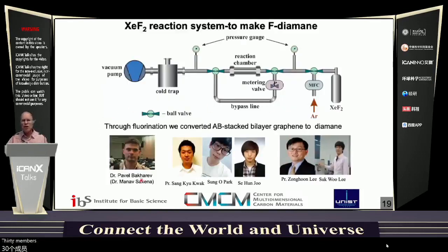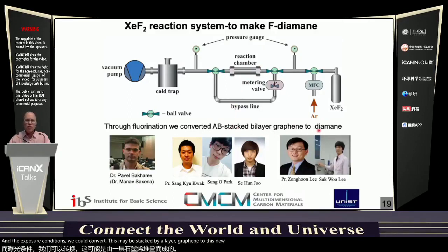So team members here work closely on this project, and we have a little home-built system. We put our AB stacked bilayer graphene, it might still be on the copper nickel, or sometimes we delaminated that and put that onto gold or nickel TEM grids. And we then could mildly heat xenon difluoride. It's a solid at room temperature, but has a high vapor pressure. And then by controlling the temperature here, also quite moderate, maybe around 40 to 50 degrees Celsius, and the exposure conditions, we could convert this AB stacked bilayer graphene to this new material called diamane.